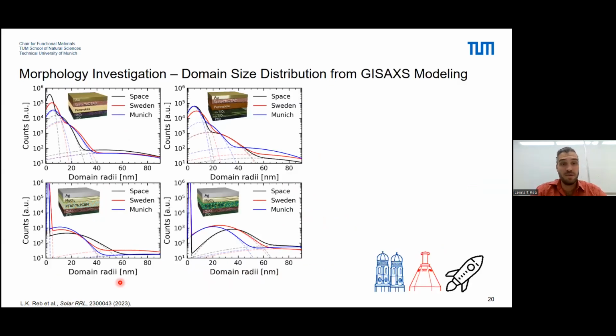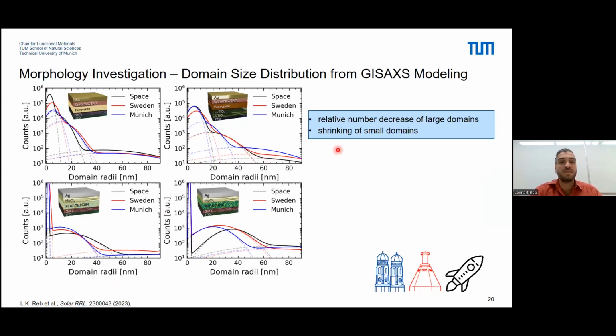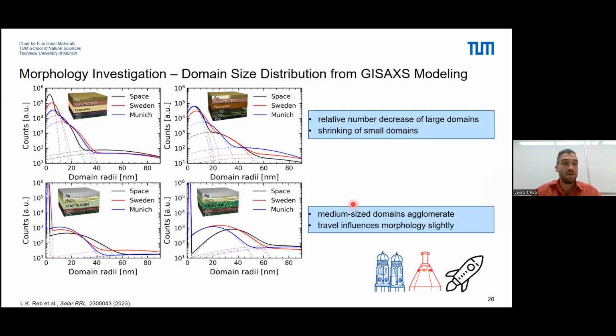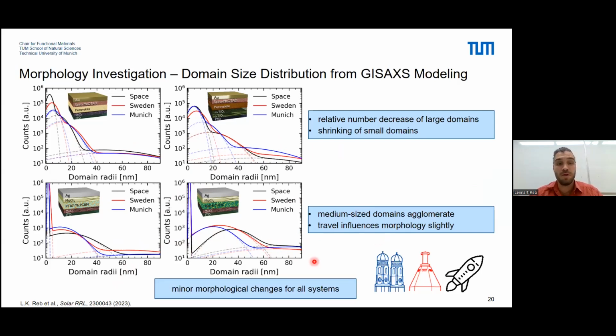Regarding GISAXS, so here I'm already showing you the modeling. We can see that for the perovskite ones, we have a slight decrease of large domains, and also small domains tend to shrink a little bit. For the organic devices, we see that basically the medium-sized domains kind of agglomerate, so they grow a little bit, and also that the travel influences the morphology already. But still, these changes that we see here, they are not strong. So it's minor morphological changes for our systems, but some changes can be observed.